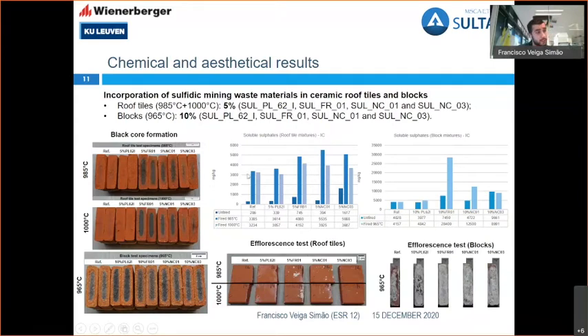So you can definitely see a similar correlation on the soluble sulfates content in the roof tiles and also blocks for the reference and also the Plombières, whilst all the other more unclean material, let's say more dirty material, have higher numbers, which also show a bigger efflorescence, salt formation. So calcium sulfate is also formed and by capillarity reaches the surface of the roof tile test pieces.